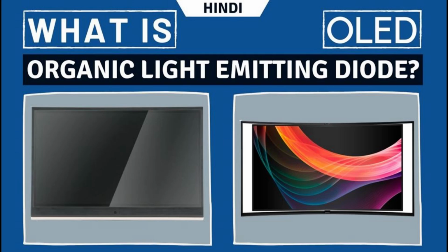The biggest technical problem for OLEDs is the limited lifetime of the organic materials. One 2008 technical report on an OLED TV panel found that after 1000 hours, the blue luminance degraded by 12%, the red by 7% and the green by 8%.